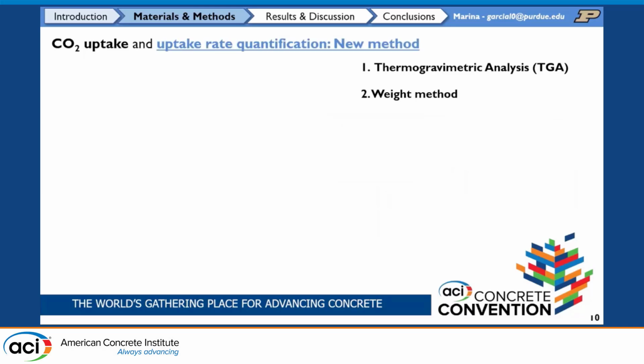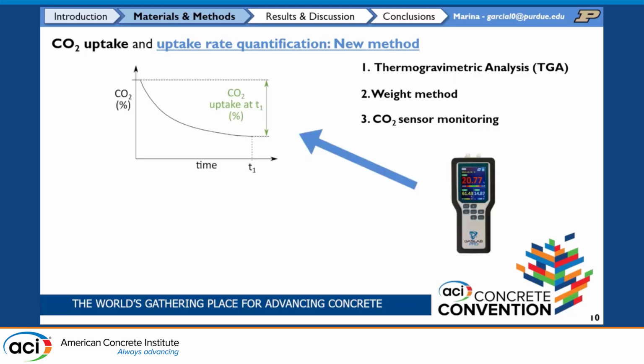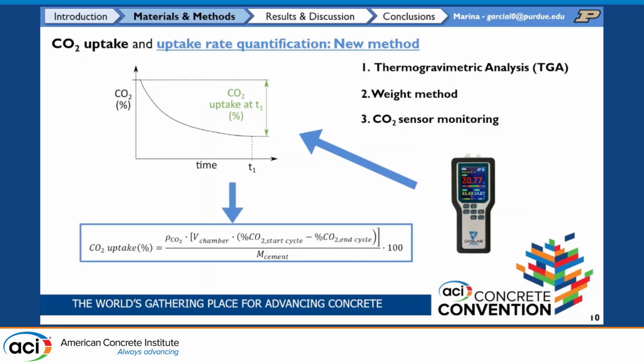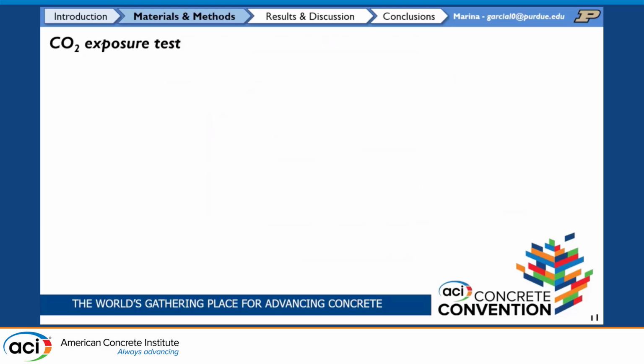So what we decided to do is come up with our own new method that will let us not only estimate that CO2 uptake, but also the CO2 uptake rate, or how fast that reaction is happening. This method, we call it CO2 sensor monitoring, where we took our CO2 sensor, which will measure over time that CO2 concentration in an enclosed environment, and therefore we can estimate how much CO2 was uptaken in our material.